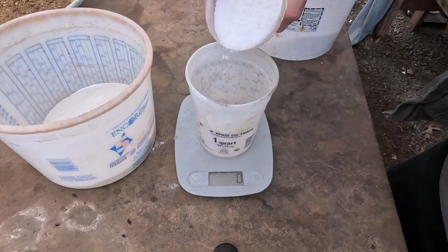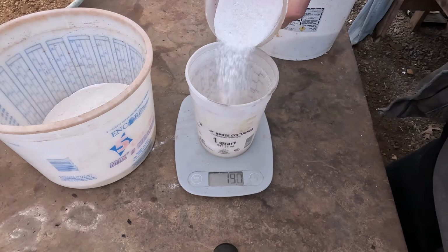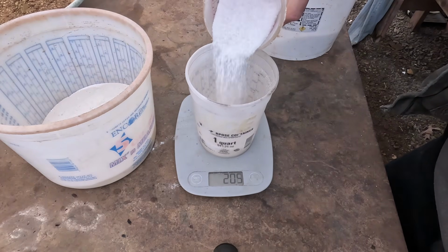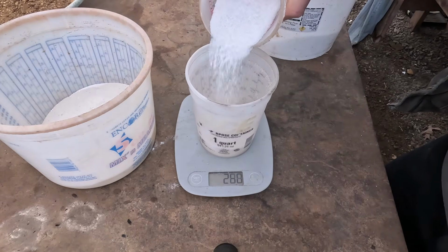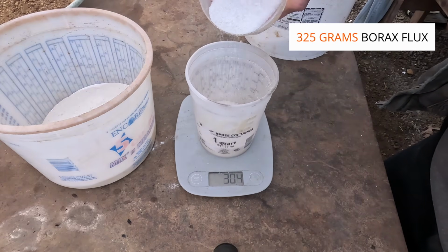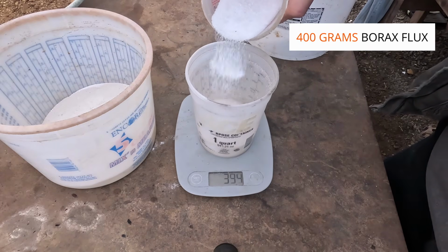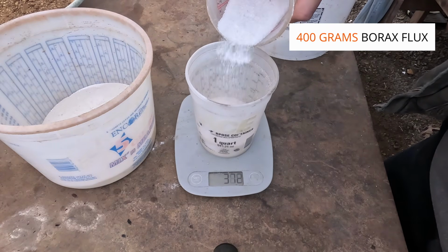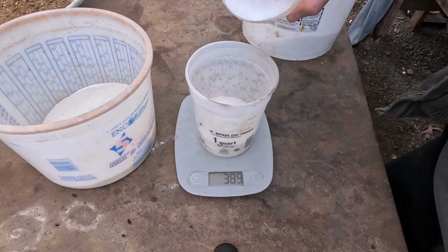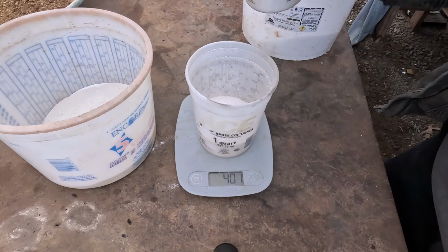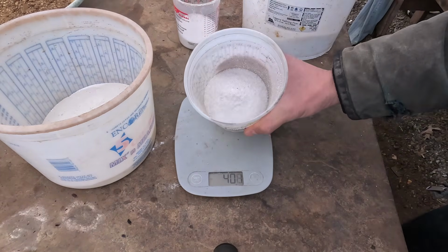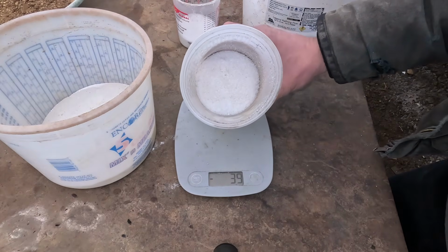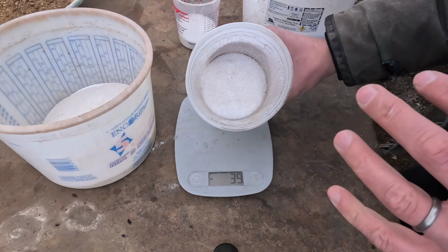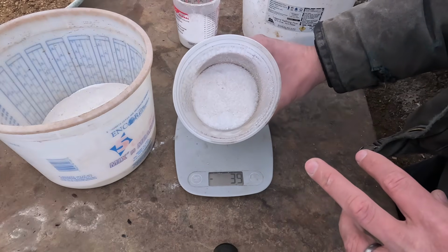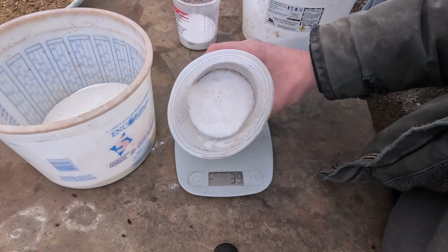Now I'm running a little low on borax, so I'm gonna use this other flux here. It has a lot of borax in it and a little bit of oxidizer. I'm gonna add in 325 grams of that. Actually, a little bit more. I'm gonna go with 400 because the oxidizer shouldn't actually count. It's not really a flux. It's just delivering oxygen to the smelt. The borax will also do a good job absorbing oxides and make the flux and the slag really fluid, so the metal can rain down to the bottom and collect in our collector metal.